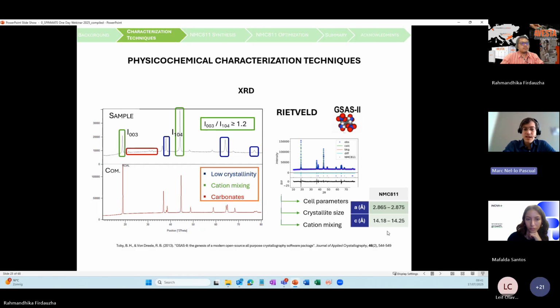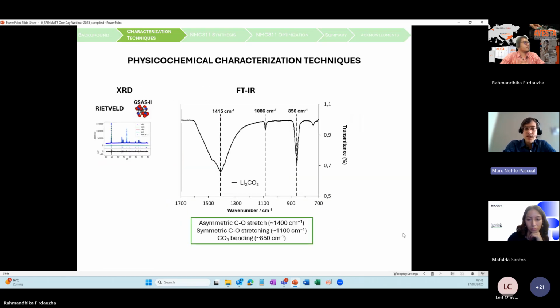There's also the crystallite size that correlates with the crystallinity of the sample, and also you can refine to have a much more quantitative value of this lithium nickel cation mixing. So this would be for the XRD technique. We can estimate this lithium nickel cation mixing that we're mentioning.